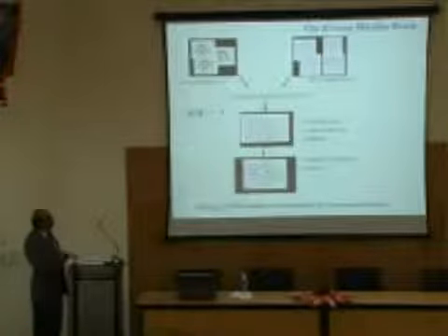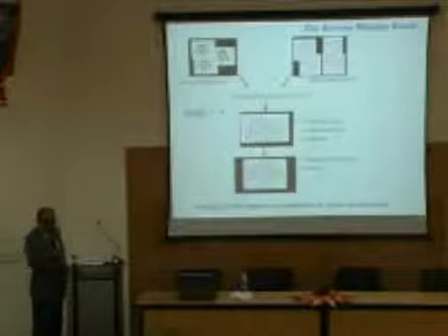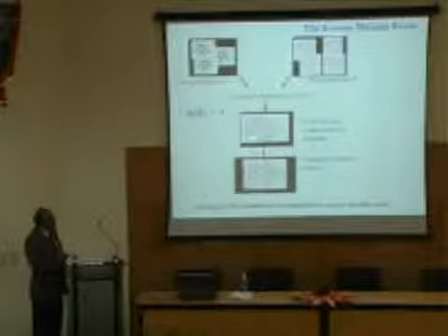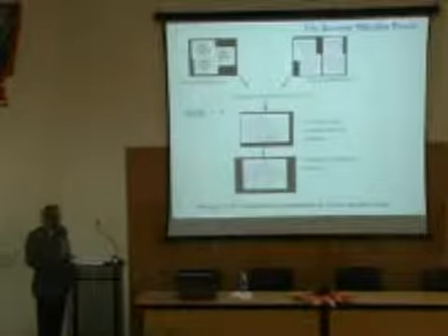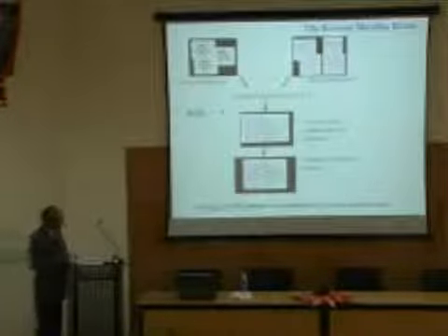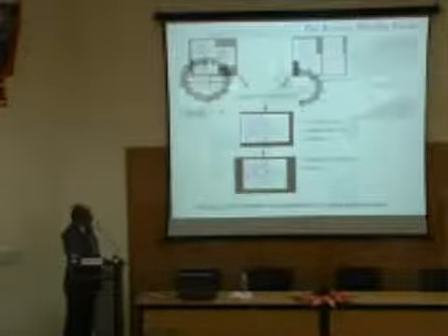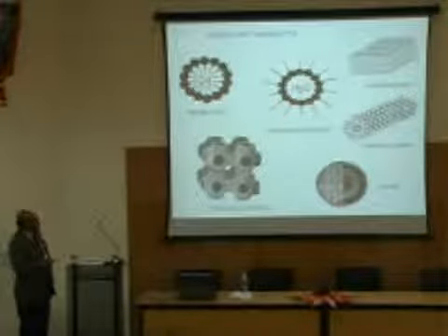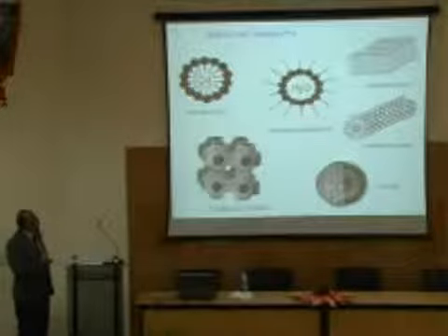So, normally if you do not use microemulsions, also you can do this reaction, but you will get large size particles. So, you will get micron size. Normal particles you will get is micron size. But if you use microemulsions, you will get same particles, but restrained to the size of the structure which you have created in solution. And so, you will get small sized objects, and this is a way of control of the size of these particles. Okay?